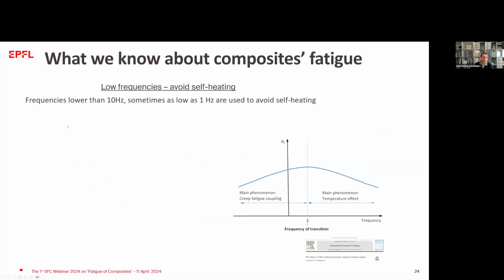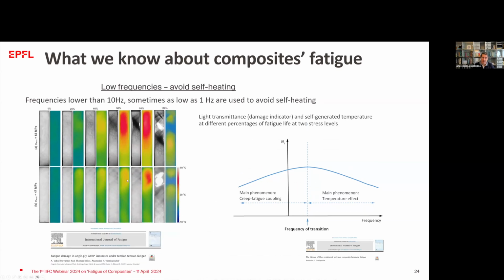You remember we discussed frequencies, and we know that there is a significant effect. Now, when we do tests on composites, we try to keep the frequency low, lower than 10 Hertz for sure, sometimes as low as 1 Hertz, to avoid self-heating. Because if we have self-heating in the material, we see that, this is a test that we did a couple of years ago here at CC Lab.